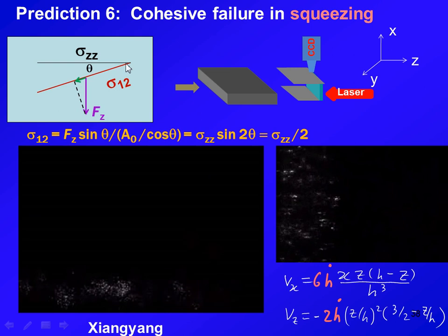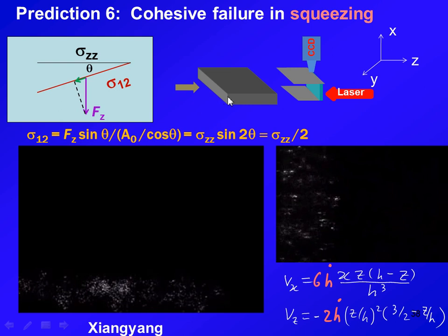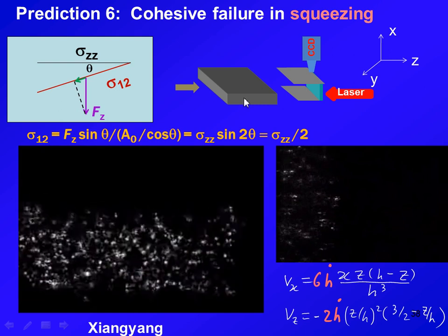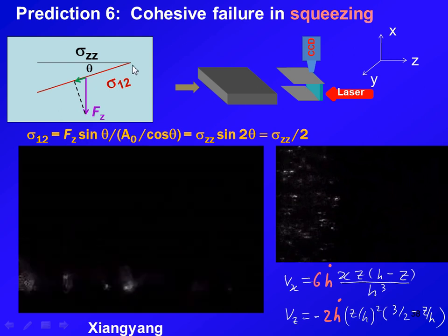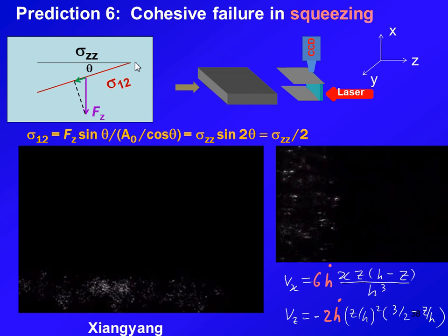And you can perform an analysis realizing that the squeezing of the sample by a surface, in this case with constant force, you can decompose that force into an inclined plane and think about a shear stress on that plane. And that shear stress, if it's high enough, could produce what I showed you in simple shear geometry, the strain localization. In other words, finding a place to undergo failure through chain disentanglement.